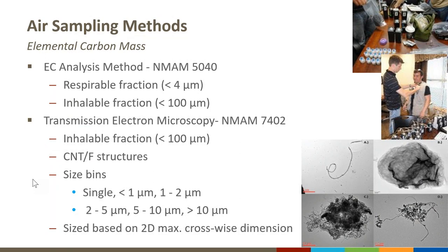So specifically for the air sampling methods, as I mentioned, elemental carbon was used for a mass-based measurement. And this was analyzed using NIOSH method 5040, which was originally designed for diesel exhaust. We collected two samples for elemental carbon. One was collected at the respirable size fraction, which predominantly deposits in the alveolar region. And then one sample was collected at the inhalable fraction, which is going to deposit more likely in the upper airways.